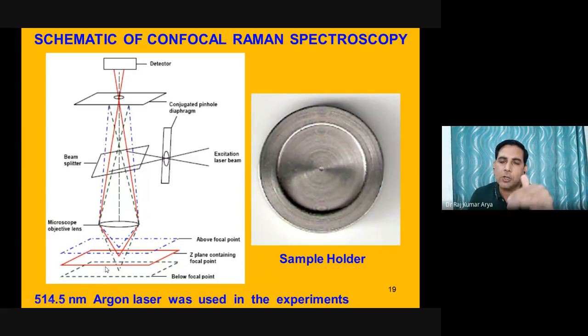holder here, locate the substrate, and then you will find a video there in this confocal microscope. You can identify your pattern there. It means you are at the substrate. In that case, first you take the spectra. If it is completely noise, it means you are at the substrate. Then make this 1 micron down or 2 micron down, so you are going inside the coating. Get the spectra, you will get the spectra for your dried film.